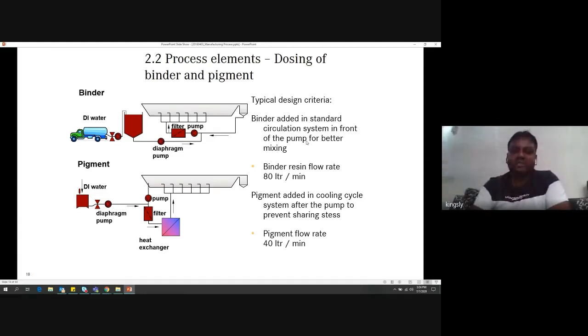Next one is how we do the dosing of this paint. How do we get this e-coat paint? We get the paint in two categories. One is the binder, then the pigment. Pigment is nothing but the color, and binder is nothing but a paste which gives the adhesive properties for the paint. Then these two are mixed with DI water. By circulation, the binder is mixed with the pigment in a uniform way, so that when you dip the car body and it comes out, you will see equivalent paint distribution over all the area.